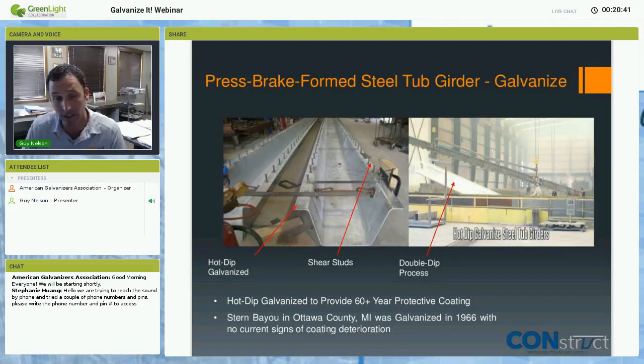We actually have one here locally in Ottawa County, Michigan. Again, Michigan likes to use their de-icing salts, and the bridge was built in 1966. Span lengths up to 50 feet long, and currently inspection reports show no current signs of any coating deterioration on those galvanized steel tub girders. So we really believe that the hot dip galvanizing really is a very effective protection for the steel tub girder.